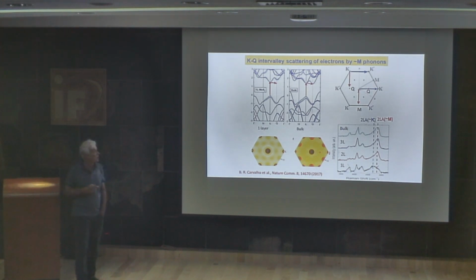Then, differently from the case of graphene, in which we only have the scattering from K to K prime, in the case of molybdenum disulfide, 2 layers, 3 layers and more, we also have the scattering from K to Q that is related to the phonons near the M point.